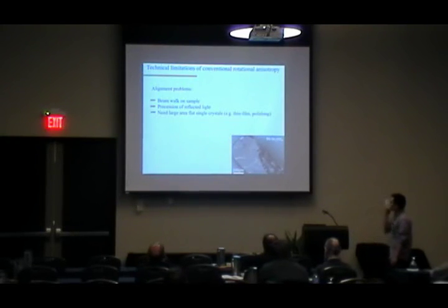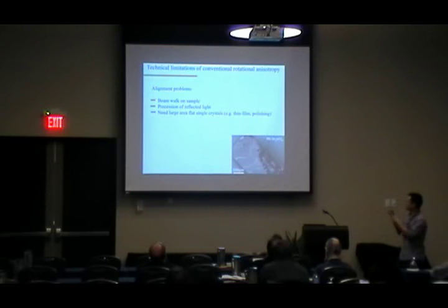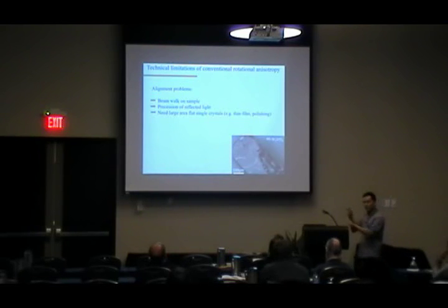So let me tell you some experimental details about how this works and why it's challenging. One of the problems is that the sample, and this is typical for many correlated electron materials, looks something like this. They're not nice, shiny, flat wafers. These are crystals that arrive in your mail millimeters in size that look like dust. You have to cleave them, and then upon looking under an optical microscope, you find terraces, cracks, and so forth. And so you've got to do that sort of rotational anisotropy measurement on the cleanest, smoothest part of the sample as you can find.